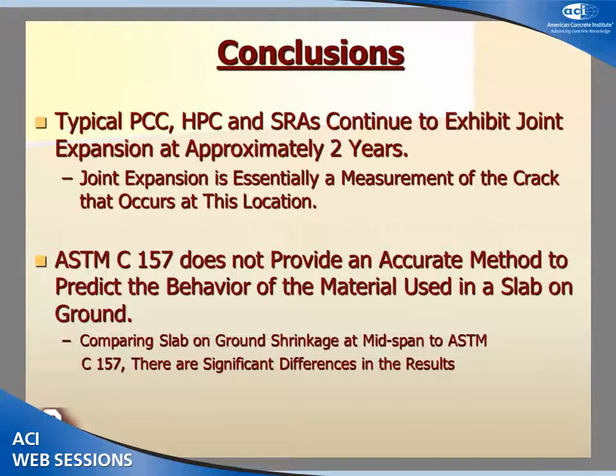Just the conclusion of my presentation: typical Portland cement concrete, high performance cement concrete, and shrinkage reducing admixtures continue to exhibit joint expansion at approximately 2 years. And as I mentioned before, this joint expansion was the crack that we measured at the location of the joint opening. We also found that ASTM C157 does not provide an accurate method to predict the behavior of material used in a slab on ground.